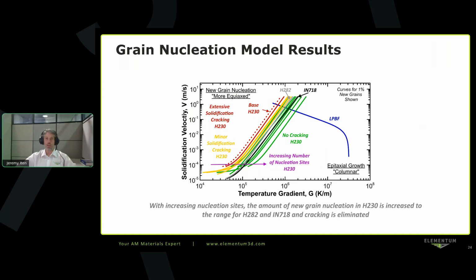And so what you want to do is you want to have your columnar to equiax transition, those colored lines, the red, yellow, and green lines, for example, or black in one case, you want those lines to be as far right as possible so that you're forming primarily equiaxed solidification rather than the columnar solidification. So the base Haynes 230, we calculated this, and we found that it's way over there with that dashed type line, and therefore you're primarily columnar solidification in laser powder bed fusion type processing conditions.